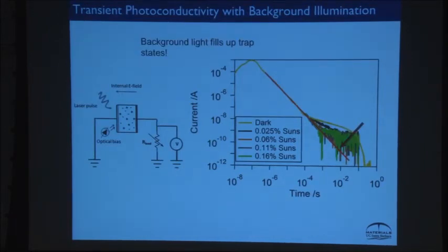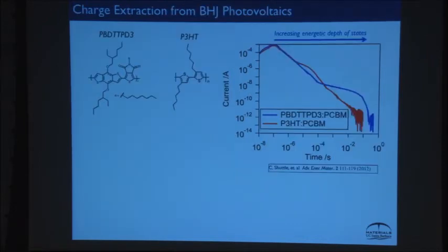But what's funny is, you can know this too, because you can actually measure this with background illumination, and there are not many of these states, right? You can do it with a little bit of light, and what happens is you can get rid of this knee, which is a deep state, just by filling up the traps. But now if I compare these two materials that nominally had the same solar cell efficiency, one of them has this knee, so this knee is the deep states, and the other one doesn't, okay? Now, it's not obvious, right? We expect that both of these should have some deep-lying states, but this one doesn't.